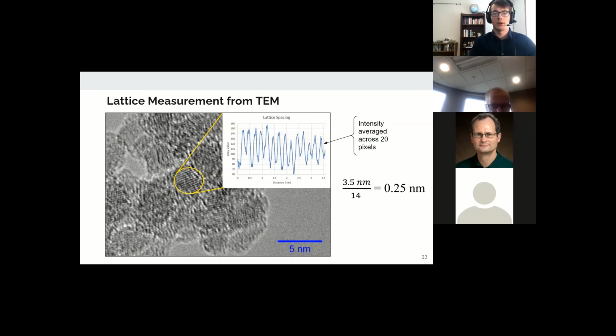TEM analysis of our samples has consistently revealed lattice spacings close to 0.25 nanometers, which can be indexed to the 111 plane of beta silicon carbide with a cubic unit cell parameter of 0.436 nanometers. This observation is consistent with universal experimental findings that the cubic crystal structure, or the beta structure, of silicon carbide is more probable than the hexagonal structure for small nanocrystals, that is for nanocrystals below about 5 nanometers.